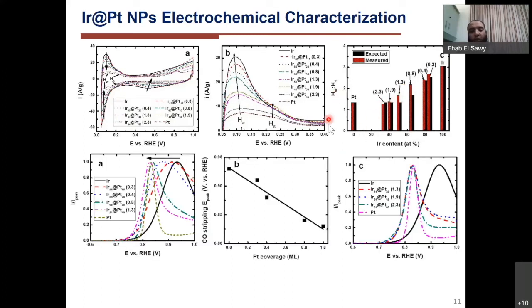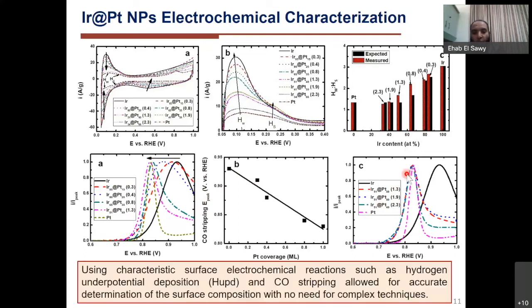We also used carbon monoxide stripping to track the surface nature. As you could see, that's the iridium core before adding any monolayer. As we keep changing the surface coverage from sub-monolayer to a complete monolayer, the carbon monoxide stripping peak shifts toward that of platinum, with a kind of linear relation between the peak and the platinum coverage. With more than one monolayer, up to 2 monolayers, the surface behaved as bulk platinum. So these simple electrochemical techniques were very efficient in determining the surface composition and allowed us to avoid using any complex techniques.